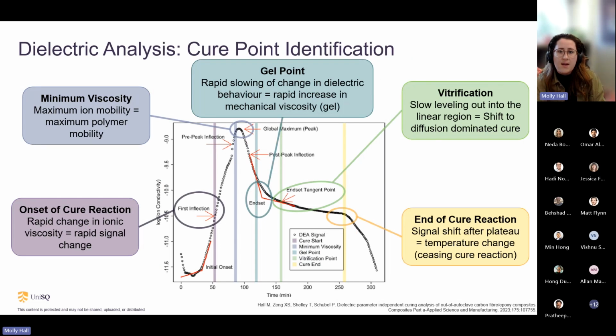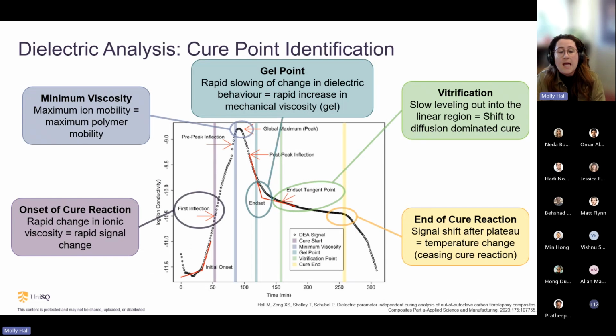The next step from that was, how do we use these and how do we tie the dielectric signal to information about what's happening with the cure? So here are the 5 methods for identifying different cure points that we proposed in one of my first papers. So to start with, that initial inflection in your signal, where you see the signal drastically rising, and because of that rapid change in the ion viscosity, that's your onset of your cure reaction. So your material is starting to move a lot and you see that rapid increase. The global maximum, or minimum in case of your impedance, is the point of minimum viscosity.